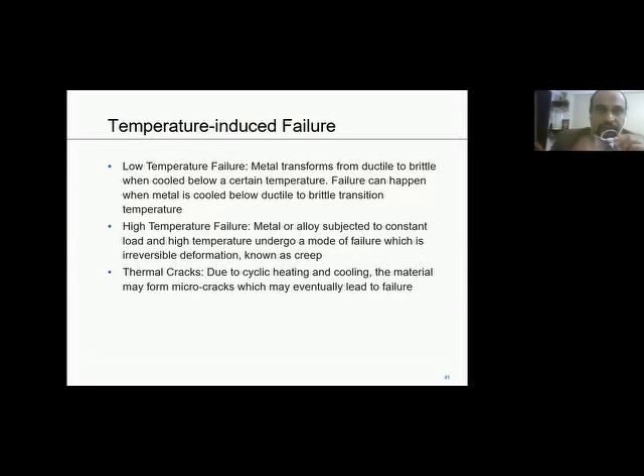Now, what are the temperature-induced failures? Low temperature failure, high temperature failure, and I discussed already thermal cracks. So, low temperature failure is nothing but sub-zero temperature failure. A typical case we can date back to is the Titanic ship. It was hit by an iceberg, and since the temperatures were freezing, the metal lost its toughness, and that's why when the iceberg hit it, there was a crack generation, and the whole ship sank. So what really happens is the material loses its ductility at a very low temperature, like sub-zero, and even ductile material behaves in a brittle manner. So that is how it can have a catastrophic failure when it is subjected to very low, sub-zero temperature.